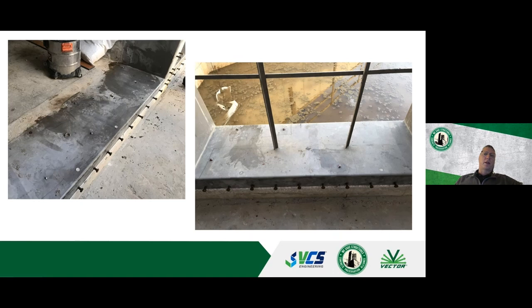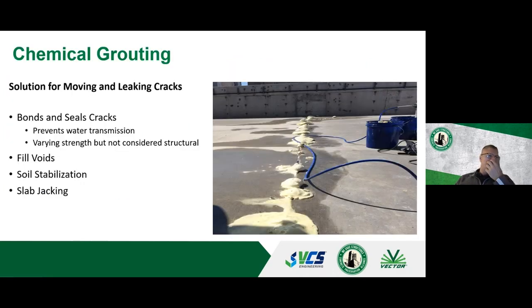cavitation occurring. The one on the right-hand side, we drilled and we injected through 6 different ports where the voids were. That injection job took us nearly 8 hours to get that epoxy resin to move through that 4-foot opening, just to make sure all of those areas were filled. It was installed very well, but there were just a few areas of voids, and we needed to do some vibrations and really move that resin along slowly.